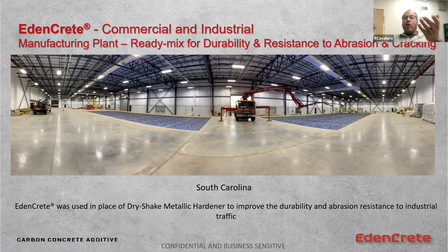Those dry shakes are going on top of, say, a 4,000 PSI concrete, and they say they make it 10,000. Well, you got a guy throwing it out there by hand. The likelihood that he gets 1 pound on every square foot across a 200,000 square foot slab is challenging. So what happens when you don't get enough in one area? It's not 10,000 PSI. Maybe it's 6,000 PSI. Maybe it's only 4. And so you get into these industrial areas where the top surface gets damaged. That top material gets chipped off. And now it may as well be an epoxy, because now you're down into the 4,000 PSI concrete, and it's going to start damaging and growing outward from that location.